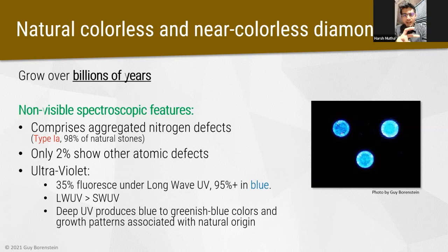And so you can see those patterns, and that identifies whether it's man-made or natural. Again, please. So with the help of that, you'll be able to tell if it's man-made or natural. If you see those lines, that means it's man-made. If you see clear shadow lines inside, a columnar effect, this is a CVD. This is actually the layers of the CVD that was grown. You see the layers inside of the strain.